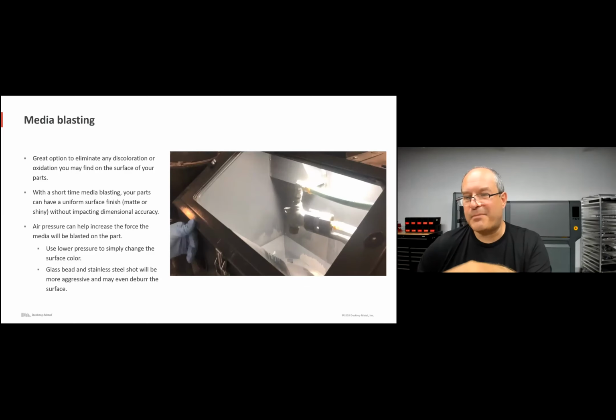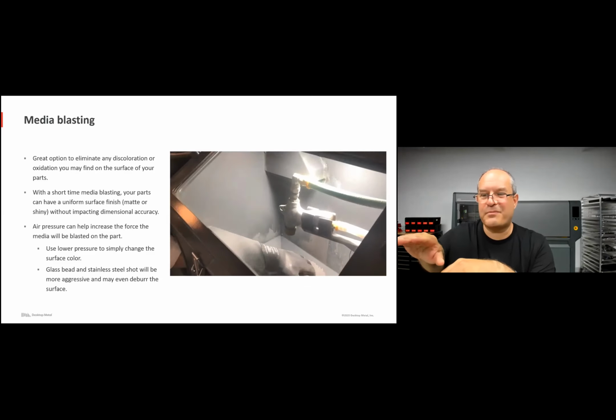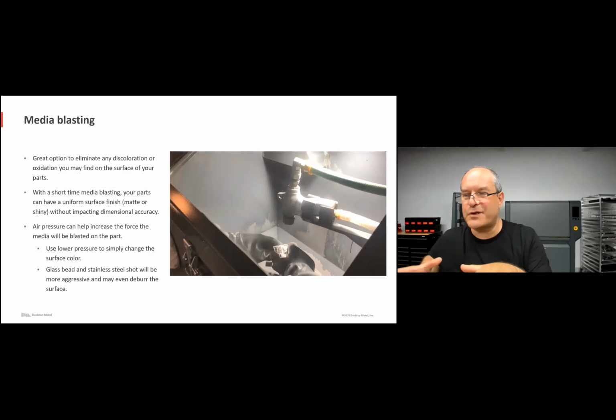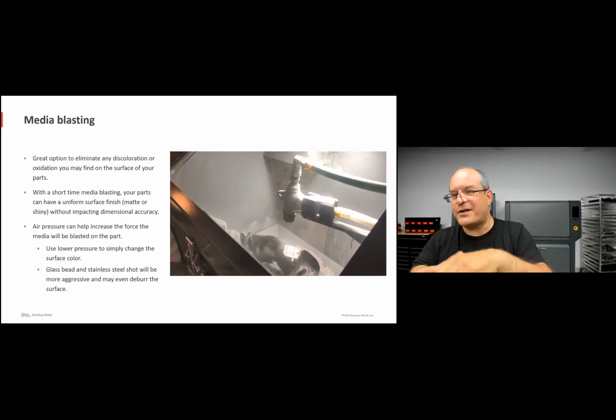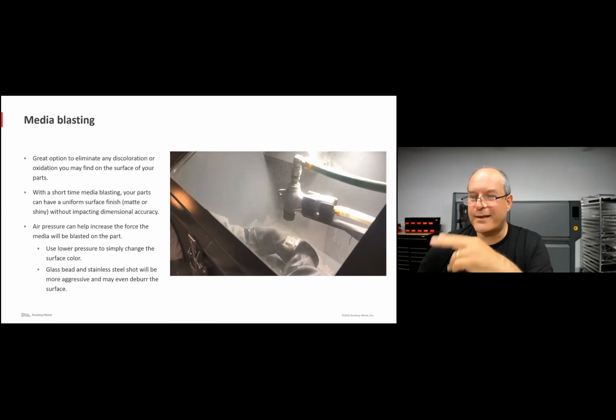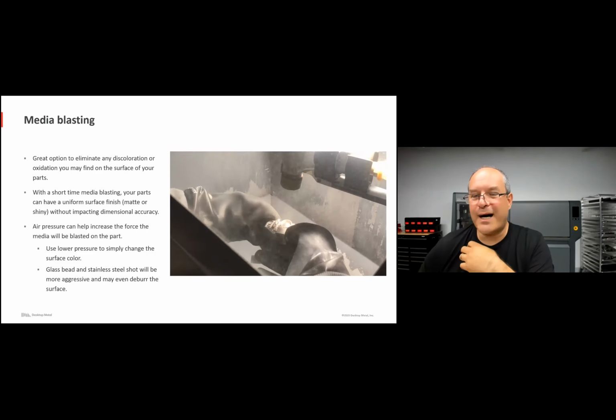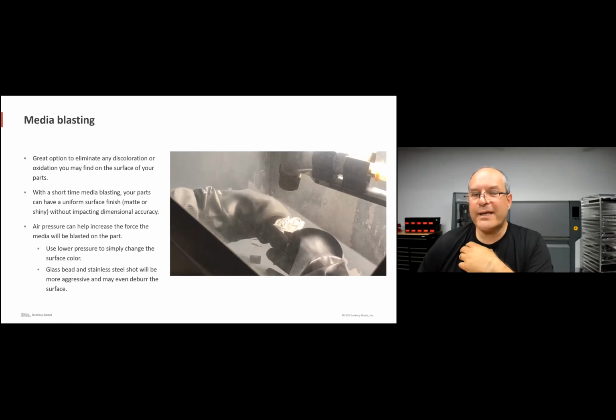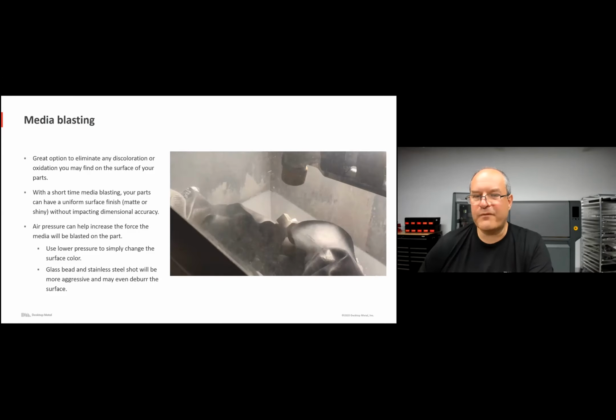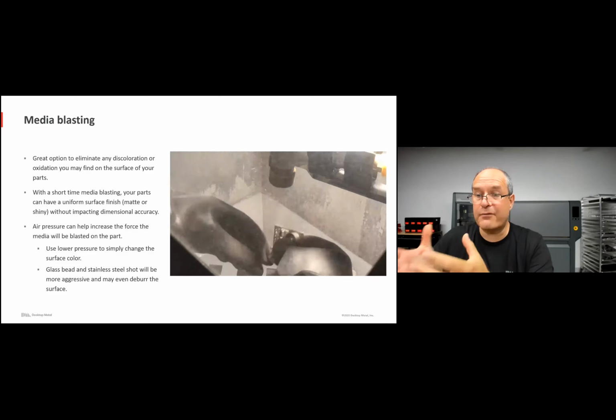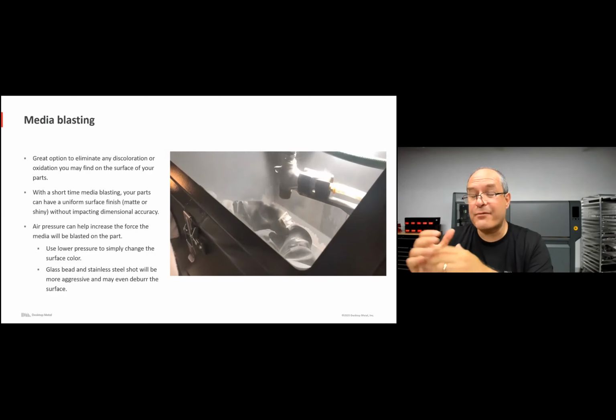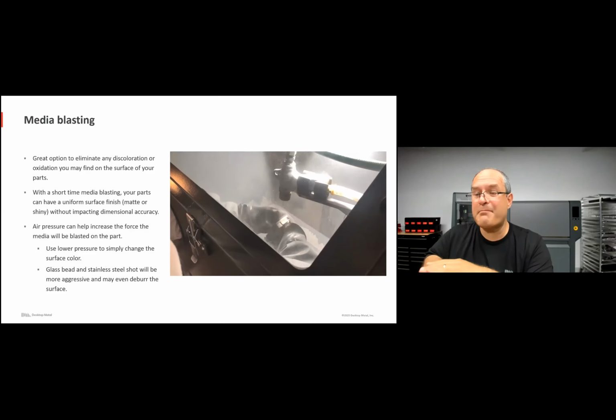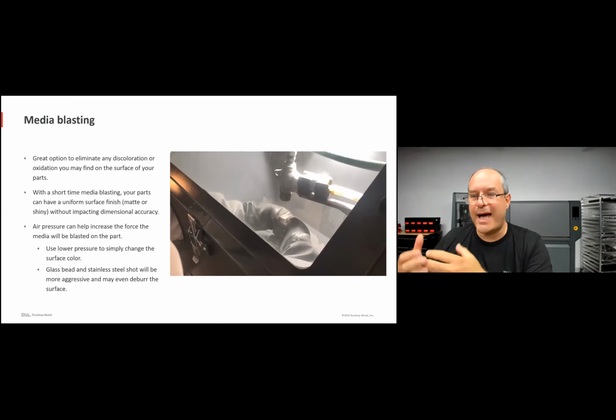You see this is a part, and the pressure is operated with a foot pedal, and so you just put the part underneath, and under pressure inside this cabinet, direct the flow onto the part. Even with a little media blasting, the parts will get a uniform finish, get rid of any oxidation or surface imperfection, and it doesn't impact dimensional accuracy on the part. It's a mild enough treatment. You're not removing tens of microns of surface, for example.